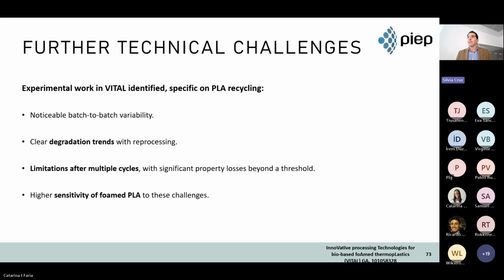What we got during these developments was a clear batch-to-batch variation when we get the material from the suppliers. That's an issue. When we work with bio-based materials, we are used to getting the same material as with fossil-based materials. When we change to bio-based, we need to take that into account because there are some slight variations from batch to batch. Of course, we have clear degradation trends on the reprocessing and massive variation in the properties of the material.